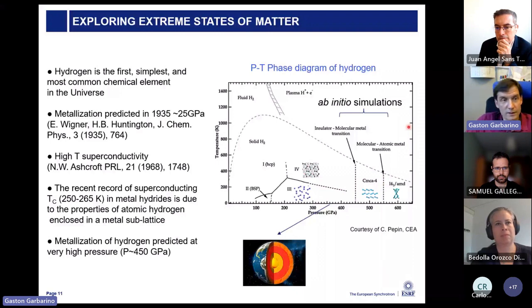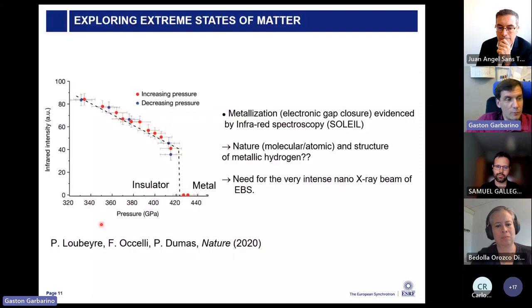For example, the most interesting case, the holy grail of high pressure, was the metallization of hydrogen, which was shown by the group of Paul Loubeyre at Synchrotron SOLEIL, where we really see the metallization of hydrogen at a pressure of 4.2 million atmospheres. This was a really important result, because it shows that we are able to reach this pressure, do measurements at these very extreme pressures, and show that this can be extrapolated to other systems.